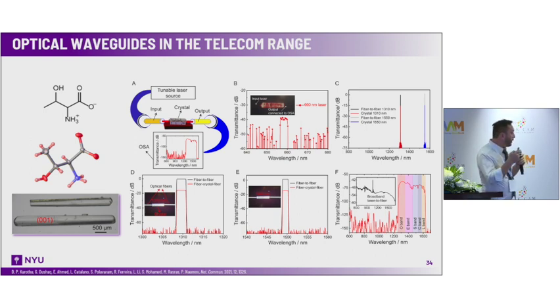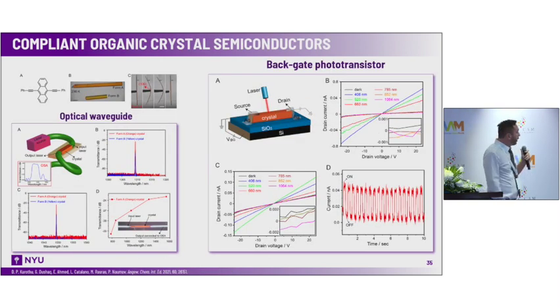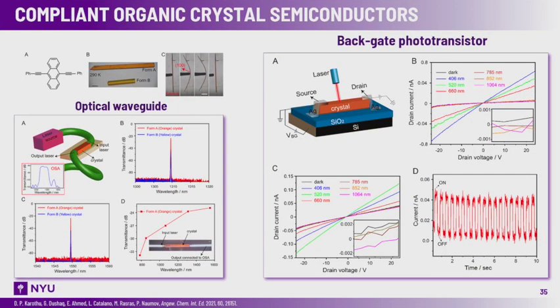So we are now expanding this, trying to chemically modify the crystal in a way to open up or close specifically part of the transmission window, in order to be able to block some information or transduce some other information. This is another example of crystals which are used as semiconductors. And this is also an active area of research where we have mechanically compliant crystals which can be bent in all ways. In this particular case, this one can be used either as an optical waveguide and at the same time as a backgate phototransistor. So we're trying now to improve the efficiency and see how we can go further by implementing phase transitions and other phenomena together and coupling them with these kinds of semiconducting properties.